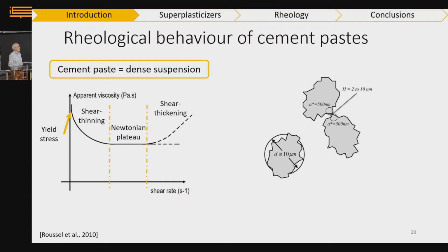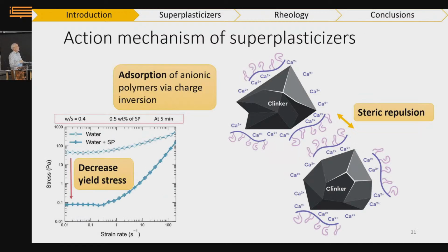And one of the manifestations of those superplasticizers, in addition to the cement paste, is to depress the initial yield stress by reducing the grain-grain interaction. And as you know, they do it by adsorbing on the clinker grain. This is not to scale at all, this drawing, but they adsorb on the clinker grain, and due to their molecular architecture, I will go back on this later, they induce steric repulsion between the grains and therefore minimize the grain-grain interactions. So in terms of yield stress, this is very clear.